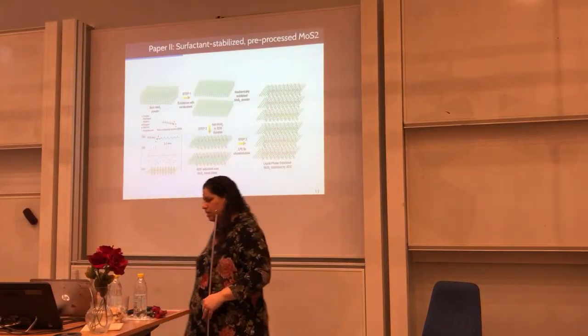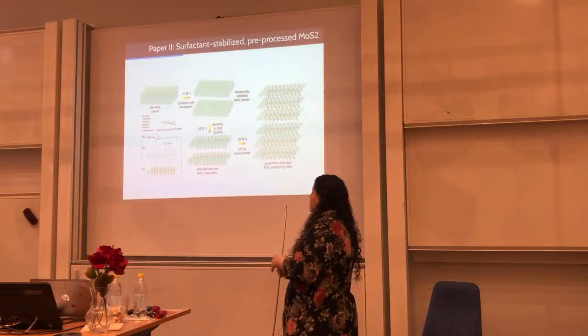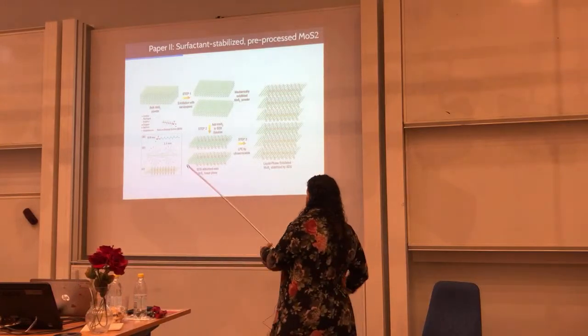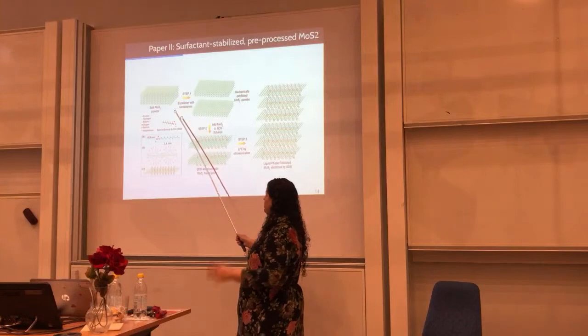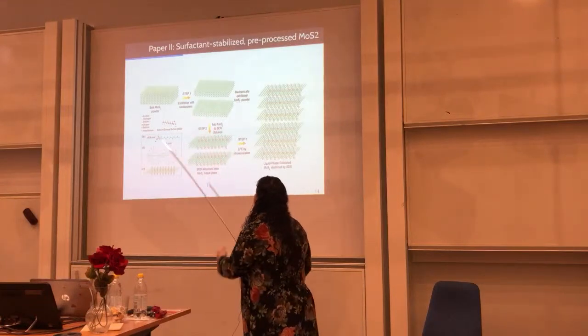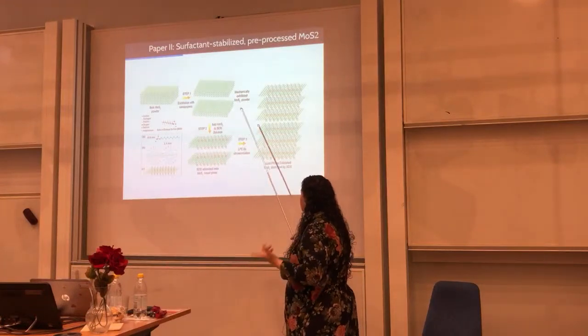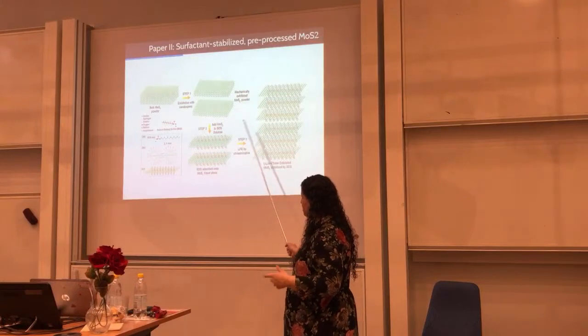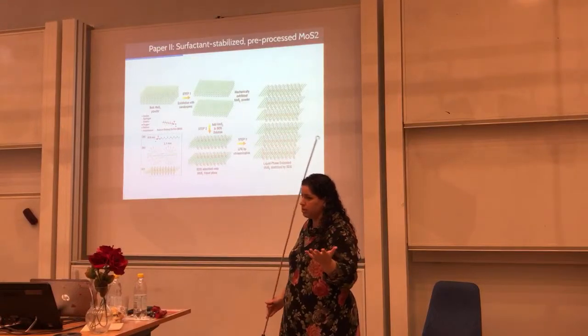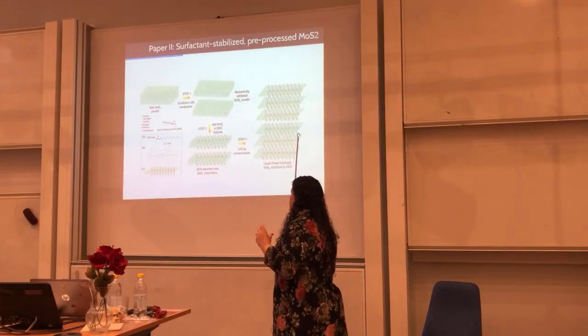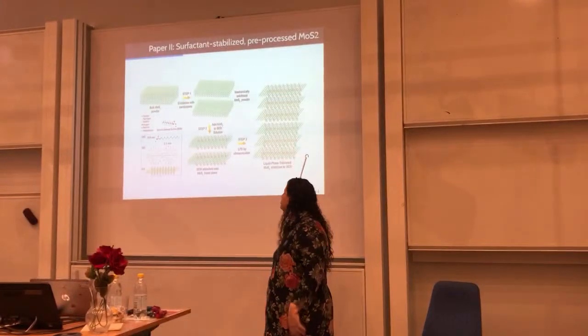And what do we do in paper 2? In paper 2, we also did this exfoliation with sandpapers. We followed the same line of thinking. But then we added these materials, instead of to water, to a surfactant solution.